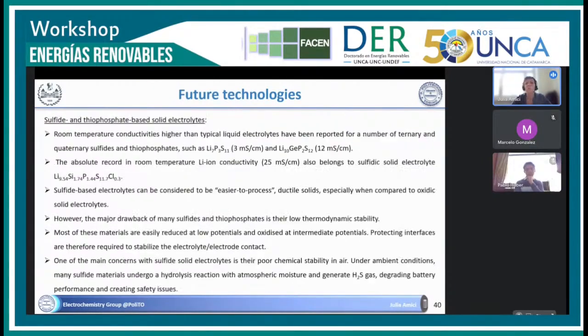For the sulfide-based solid electrolytes, the room temperature conductivities are even higher than typical liquid electrolytes. This is really interesting. We are talking about, for example, 3 millisiemens per centimeter. And the absolute record is this material with this composition, which has a lithium conductivity of 25 millisiemens per centimeter. So it's really high. It's easier to process than the previous oxidic solid electrolytes, but the problem is that it reacts really easily with metallic lithium, but also, for example, with moisture from the air, and it forms H2S gas, which is actually a poison. So this is an issue.